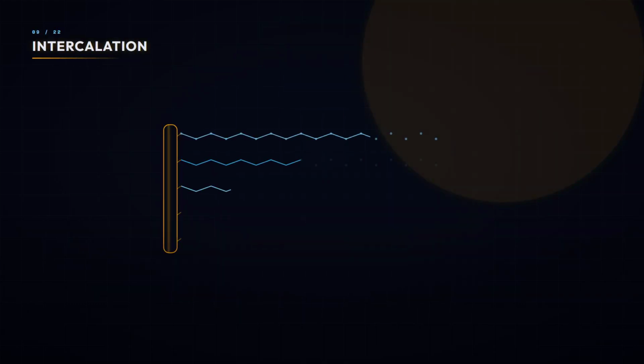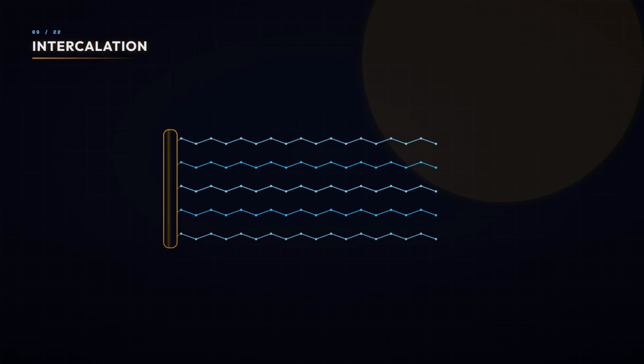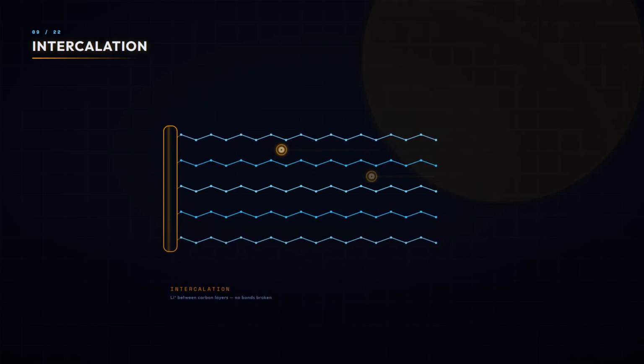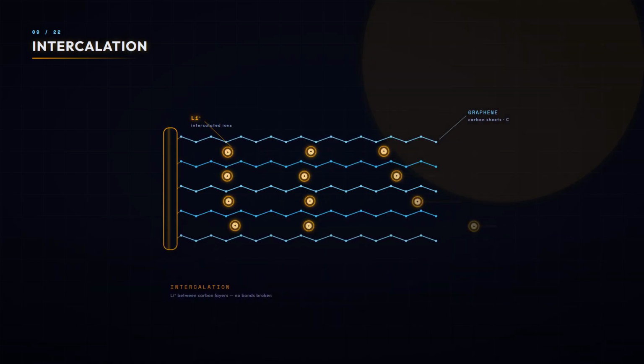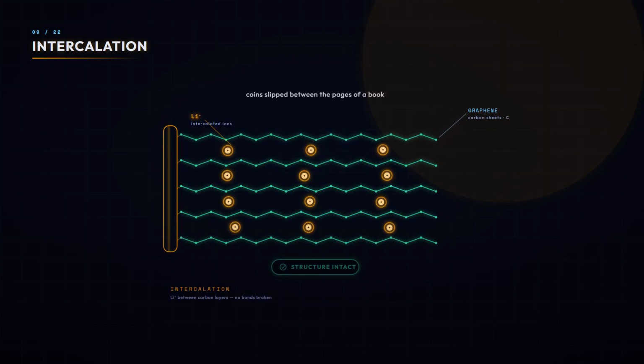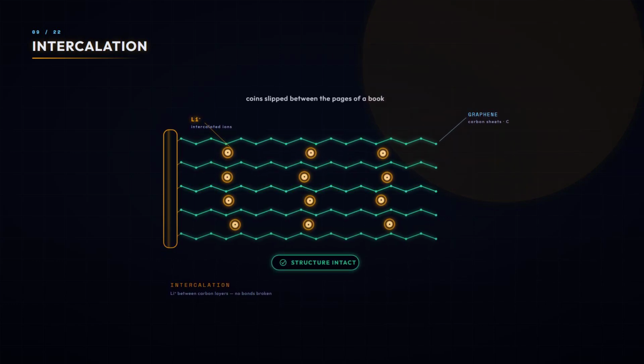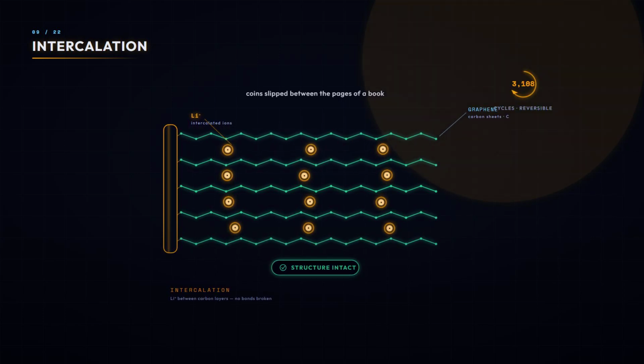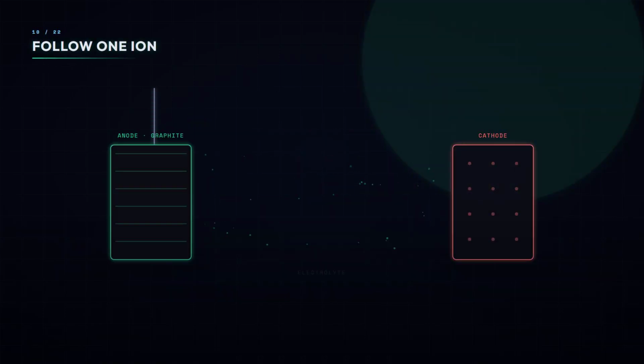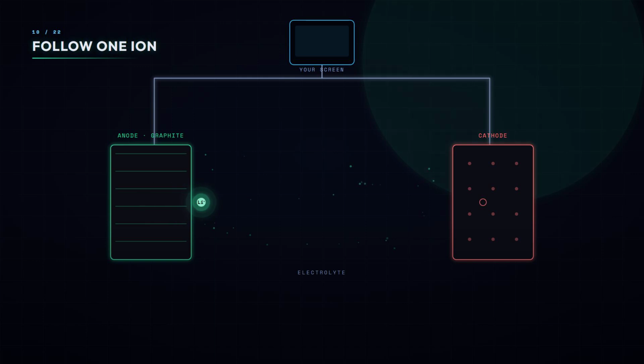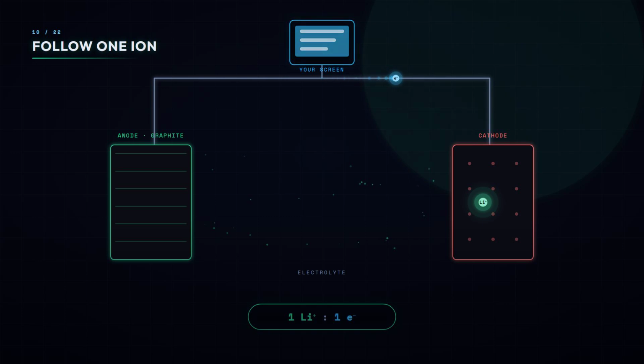How does graphite hold the lithium without breaking? By intercalation. Ions slide between the carbon sheets like coins slip between the pages of a book. The structure stays perfectly intact, which is exactly why the whole process can repeat thousands of times. Watch a single-ion discharge. It pops out of the graphite, swims across the electrolyte, and nestles into the cathode. For that one ion, exactly 1 electron is pushed through the outside circuit, lighting your screen on its way past.